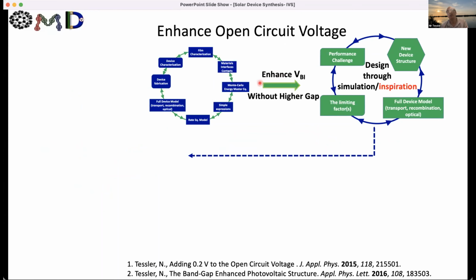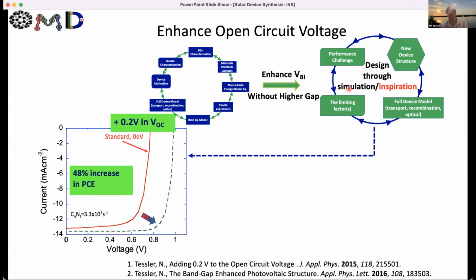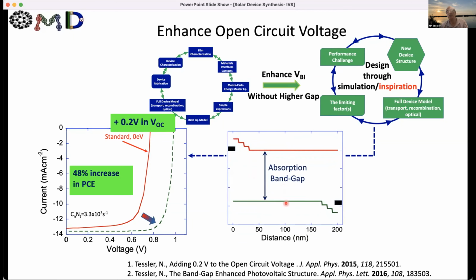So really, this was when we first implemented this cycle in the context of solar cells, going towards trying to find a solution for how to enhance the built-in potential, using the same absorber, not enhancing the band gap of the absorber. And we managed to come up with a device, and while we did the simulations that can be found in the two papers below, you can see that we plugged in the properties of P3HT and PCBM, and we managed to get a really nice enhancement in the open circuit voltage. And the interesting thing is that the device structure, or the energy level diagram that we came up with, is not intuitive at all.